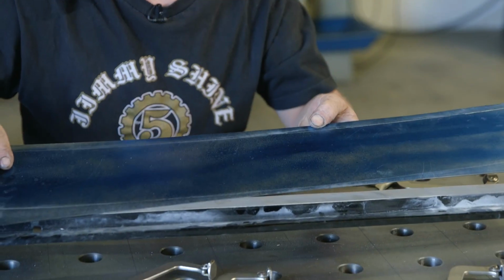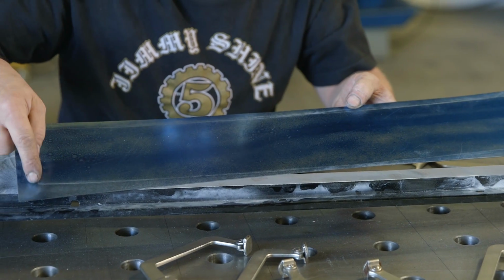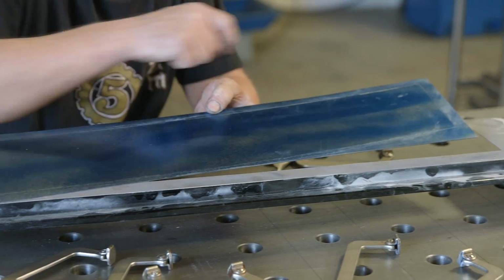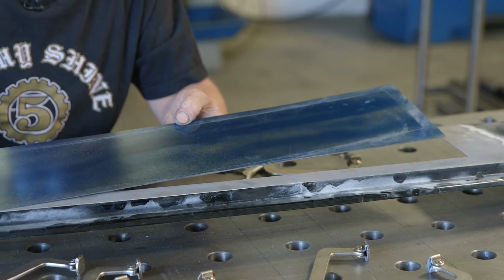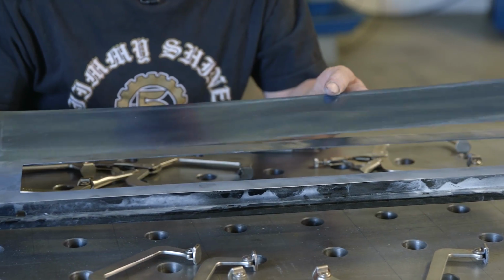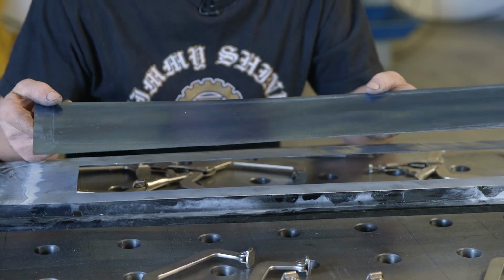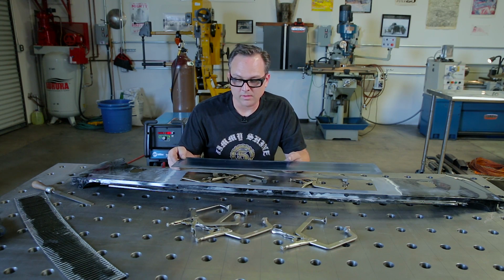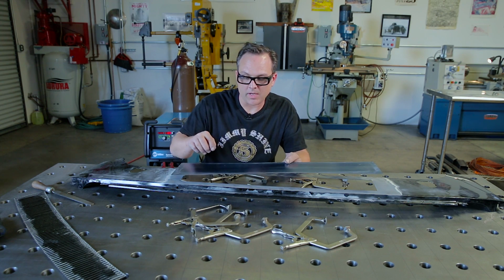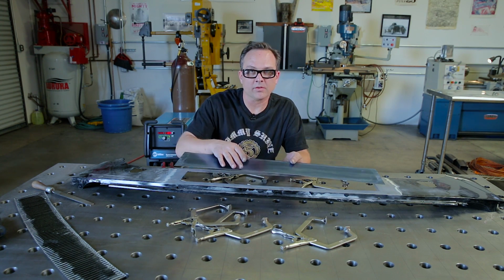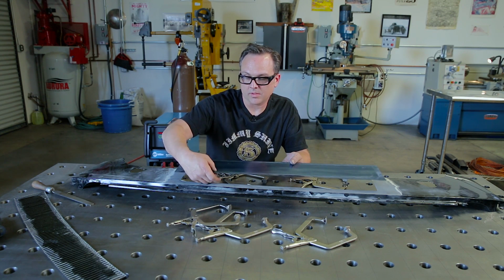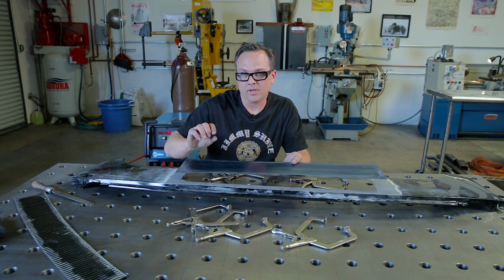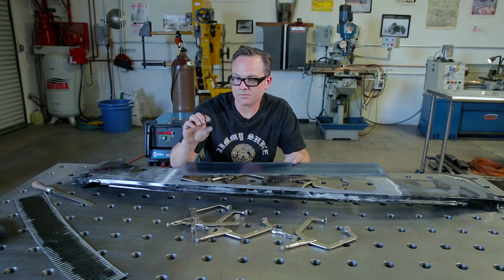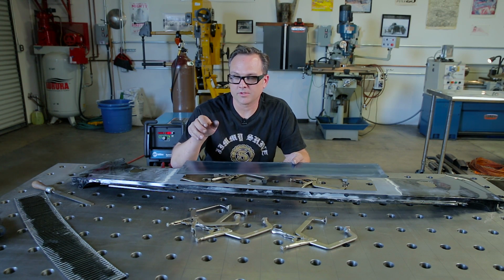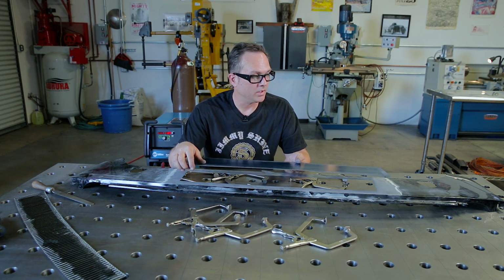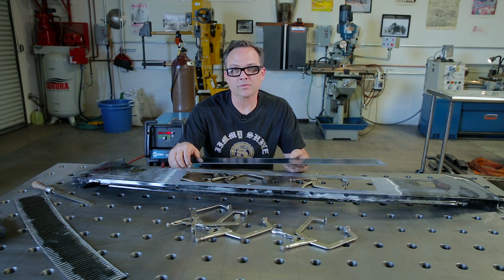Now you can see we have a scribed line all the way around. It's very, very accurate. If we can cut as close as we can to that line, then it'll be almost a perfect fit. After we put it back in there, we'll tack it in a few spots, and we'll hammer it together, and it actually can peen the metal at that gap and make the gap even closer. What it does is it squeezes the metal so that they actually get closer together, which just helps our weld that much more.